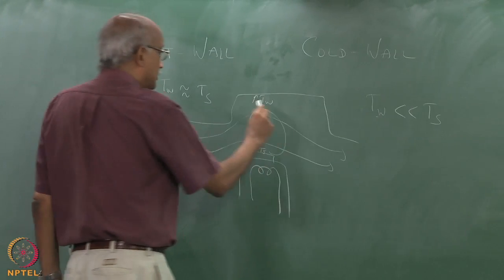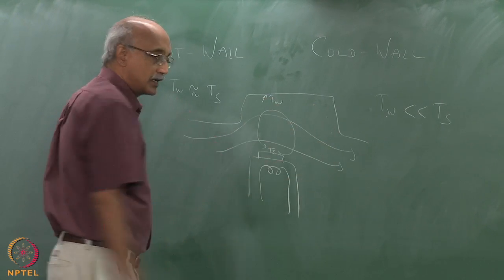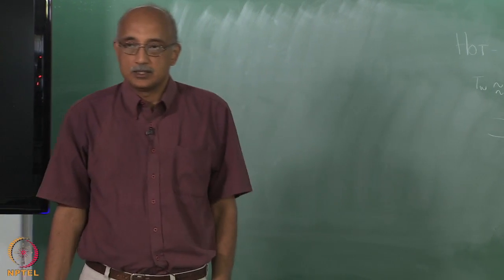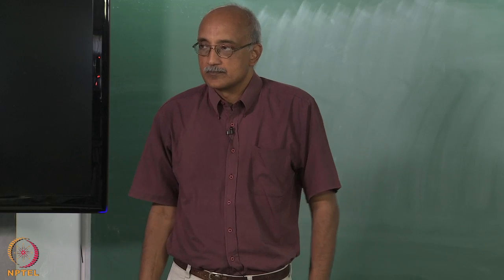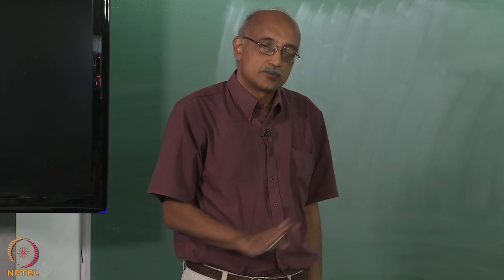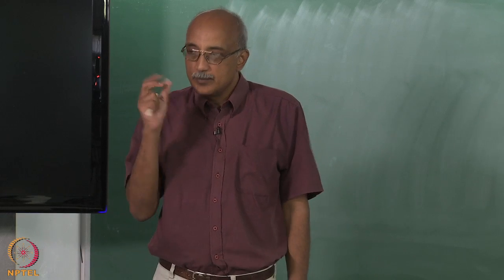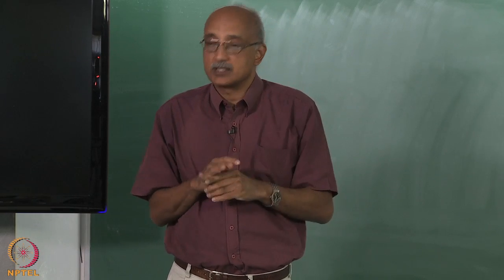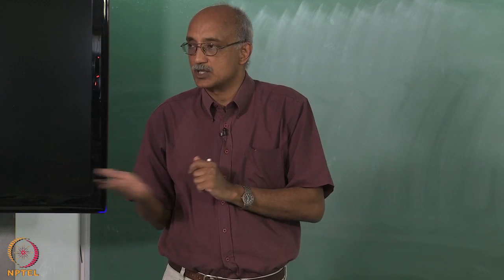Because in this configuration, all the rest of the reactor is at a much lower temperature. So, thermodynamically and kinetically, the formation of condensed phases is not favored. In a cold wall reactor, you can pretty much rest assured that you don't have to worry about the formation of the condensed phase in the bulk gas, and then the transport of these particles to the substrate, which can obviously degrade the quality of the film.